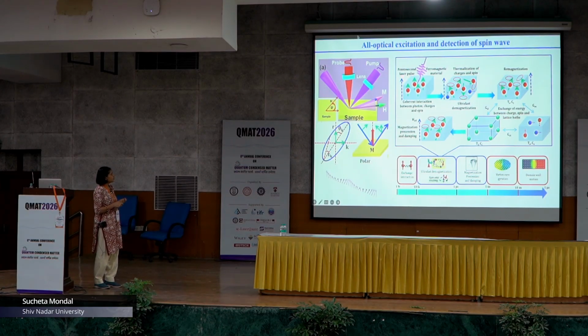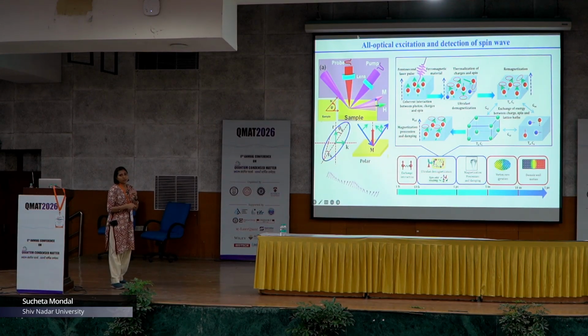So, what happens when a femtosecond pulse approaches the ferromagnetic material? The spins are aligned, and the pump pulse hits the sample in the presence of a magnetic field or without it; the thermalization will take place anyway. Okay. So, the ultrafast demagnetization is the first phenomenon that we should observe, within a few hundred femtoseconds for most of the materials. Then a remagnetization takes place. The remagnetization involves 3 degrees of freedom: the spin degrees of freedom, the electron degrees of freedom, and the lattice. So, remagnetization happens in 2 steps: one is called the fast remagnetization, another is the slow remagnetization.